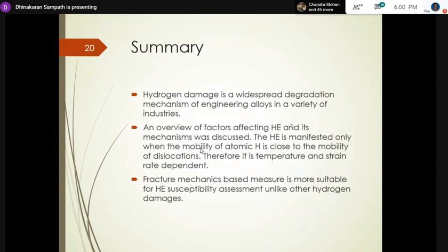If the hydrogen is not moving with the dislocations, it's not going to create any kind of problem, because when a dislocation moves and hits an obstruction at high velocity in the presence of hydrogen, it's going to create stresses. If they are not coupled, then the effects are minimum. Therefore it is dependent on temperature and strain rate. That's the key to remember. And then of course fracture mechanics specimens are useful, but some new simple methods are always sought after.